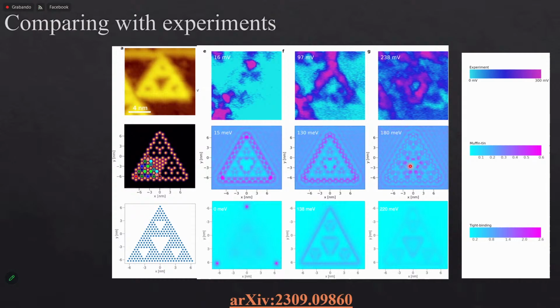But for us, it's quite nice because you could use a very simple model with just spin-orbit coupling, basically, and show that these states both appear just when you have spin-orbit coupling. And they also follow this kind of energy distribution that points quite a lot to these states being topological. So this, for us, I think, was a very, very nice result. It's something that we are very, very happy with.